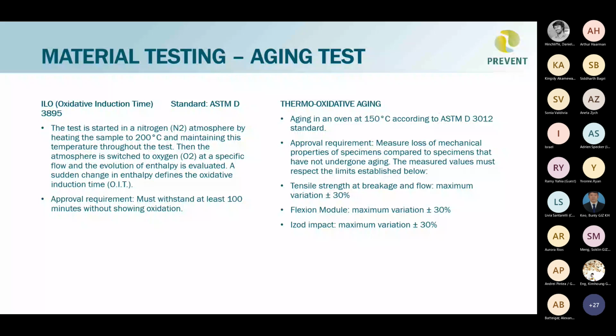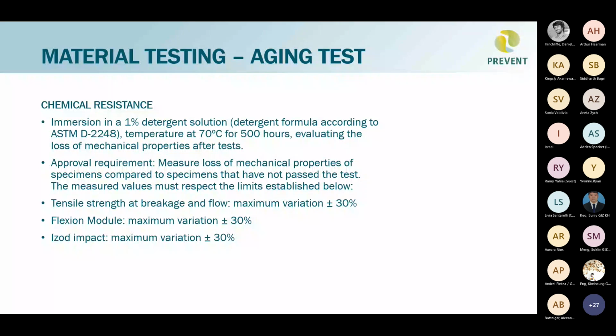Chemical resistance. So we will immerse a sample in a 1% detergent solution at a temperature of 70 degrees for 500 hours. Wow, that's long. Evaluating the loss of mechanical properties after the test. Again, you have some criteria to check: tensile strength, capacity of flexion, the impact test. You should not have a variation that is more than or equal to 30%.